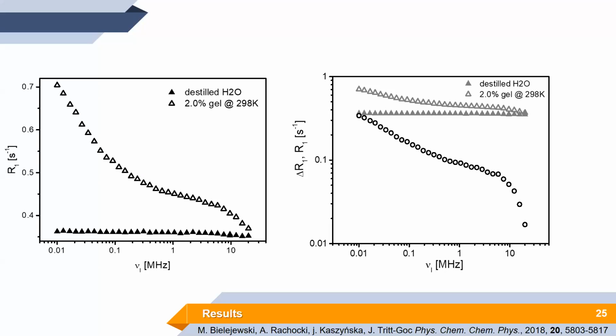In that way, somehow we ruled out the influence or the contribution from the liquid which stays in the pores of the gel matrix and behaves as a bulk solvent. And we are more sensitive now to the contribution coming from the solvent molecules at the surface of the gel matrix, interacting with the gelator molecules or very close to the matrix surface. And here on the right, you can see this profile. So this is the effect of the subtraction. And later in this presentation, I will show you this type of NMRD profile.